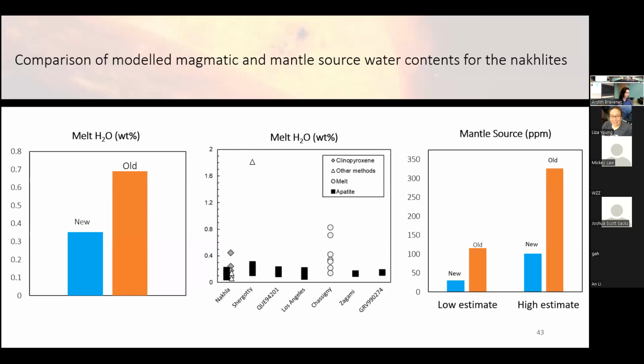And here's what the outputs of this modeling actually results in. So we see that the magmatic water content is probably going to be under 0.5 weight%. And this is only from clinopyroxene, but we can compare it to other melt water content estimates from other methods, such as apatite, directly from the melt, and so on. And it plots really favorably. It looks like most of the estimates are going to be under 1 weight%, and most of them in fact fall under 0.4 weight%. So this is starting to paint a consistent picture of what those parental melts might look like.